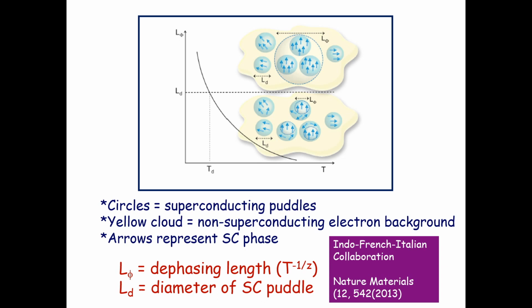The other length scale in the system is L sub D. So, what we have is these low mobility carriers are actually forming this uniform background of electrons, the yellow one. And the high mobility carriers, whose number is very small, are undergoing condensation, making superconducting droplets. The size of the droplet is L sub D, and it turns out that here the phase correlation length is actually smaller than the size of the droplet. Phase correlation length is the length over which the Cooper pairs are represented by a spin here. So, all the spins are lined up in the same direction, they are all talking to each other. All the action is inside one puddle.